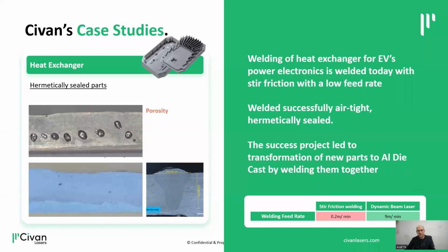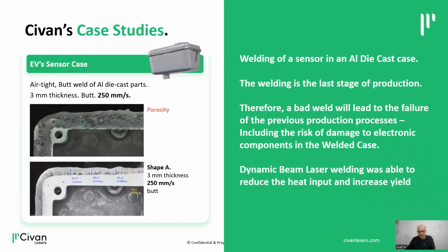In the following case studies, we display two applications that require a completely sealed part. The first application is a heat exchanger, where we started the process with robust and large porosity, but upon tuning, we eliminated most of the porosity and the sample holds the required pressure. The second case study is a sensor case very similar to the first, in which we also eliminated most of the porosity and welded at 250 millimeters per second, much faster than any alternative. The sample again holds the pressure required by the customer.